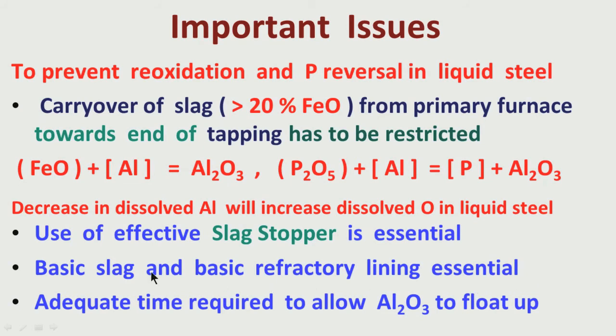So basic slag is required to take care of the alumina, the deoxidation products. So basic slag and basic refractory are also essential requirements. And then I have told you that adequate time, say about 15, 20, 25 minutes, is necessary for argon purging to allow the alumina inclusions to float up and get absorbed.